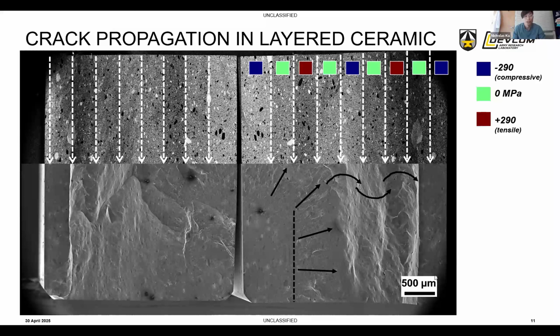So the fracture origin is along the center, and these are mirrors of the two ends of the fracture surface. What you can see is, where it fractures, you get a pretty clean fracture region, but on the back end of the bar during flexural, when it failed, you can begin to see a wavy pattern, and that seems to correlate pretty well with the different layer thicknesses. So something about that residual stress is affecting the way the crack propagates through the material.